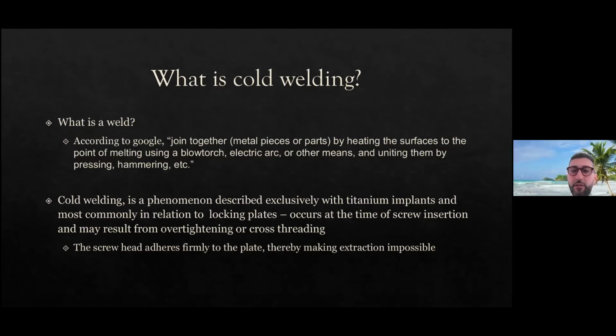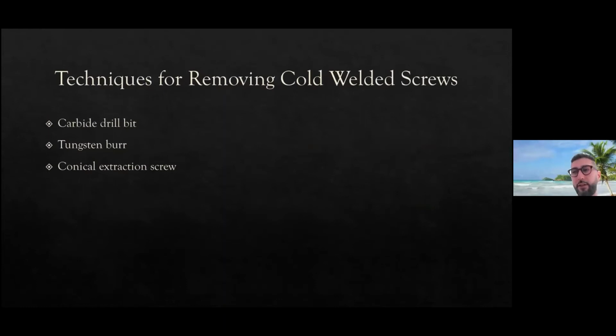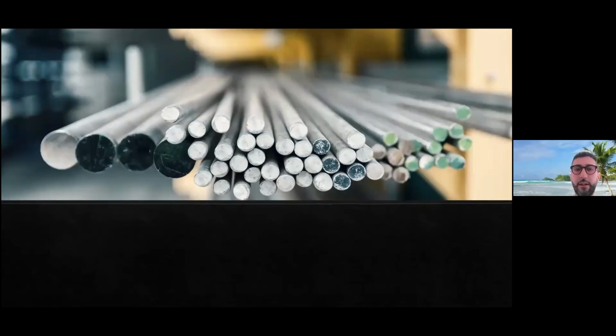So that's a phenomenon described exclusively with titanium implants, and most commonly in relation to locking plates, where you insert the screw, maybe apply too much force, maybe cross threading, but basically the screw head adheres firmly to the plate, making extraction impossible. And if you actually look at a sample, and there were a couple pictures in the study, but they didn't come across really well, so I didn't include them. But it looks like a weld. One part of the metal is indistinguishable from the other. And so, if you encounter this, which I don't think I have yet encountered, they suggest using carbide drill bits, tungsten burrs, conical extraction screws to take these cold welded screws out.